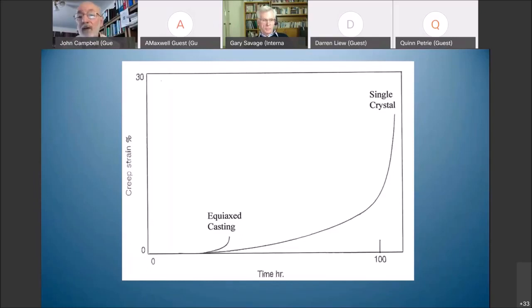And that's the reason for this enormously different performance in terms of the amount of creep and the length of time that this will last. I mean, it's an order of magnitude better properties than the equiax casting that's full of bifilms. This performs well because it has very few bifilms. Interestingly, it still goes bang. And so up here at the point where it finally fails, it finally comes apart.